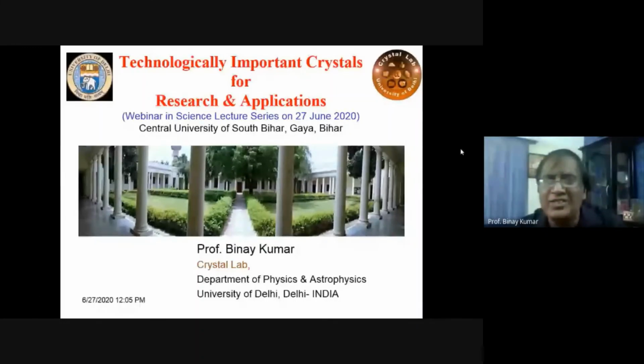So what does it mean? If I grow organic crystals by the solution method, we will get a crystal which is 2 to 3 or 4 or 5 millimeter, normally 1 to 2 centimeter in size, which can be grown as a cylindrical shape so that we can take out the wafers. So this is the importance.